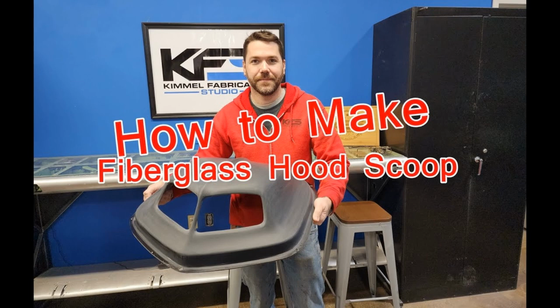Dilute the polyester resin. Note that immediately after adding the hardener, the resin will begin to solidify. Therefore, do not dilute more than 300 milliliters. Impregnate the laid fiberglass with a brush. Do it in such a way that no air bubbles remain. Sand with 80 grit sandpaper to grind off the resin buildup. Treat the joints particularly carefully, but do not rub off the fiberglass at the overlap.